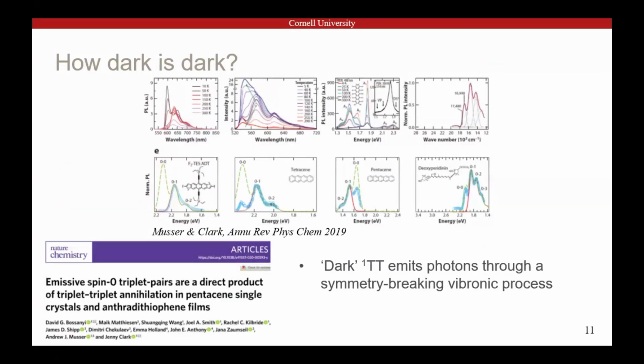You can get this unique redshifted emission in polyacenes, heteroacenes, carotenoids, and polyenes that are all characteristic of this triplet pair state directly emitting photons, not going back into the singlet. And we realized this happens through a symmetry-breaking vibronic coupling, similar to Herzberg-Teller coupling. So this TT state couples to the singlet, borrows its intensity, you get a new mixed potential energy surface that allows it to emit.